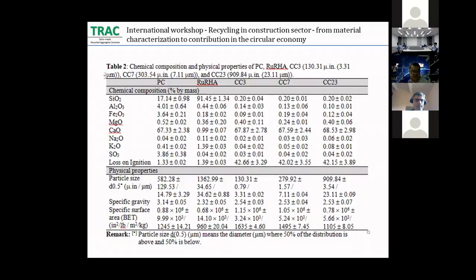By comparison, CC3 is the smallest size, CC7 is a bigger size, and CC23 is bigger than CC3 and CC7. The specific gravity of the CC materials is similar, at around 2.54. Furthermore, the specific surface area, determined by the Blaine method, is around 1,600 for CC3, 1,500 for CC7, and 1,100 for CC23.